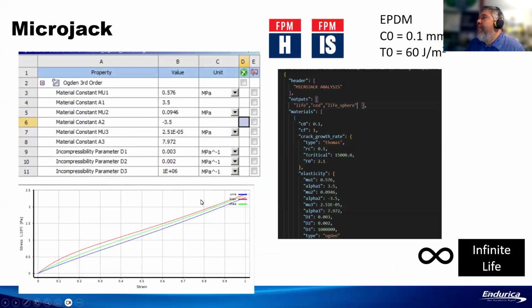So here's an example of the materials characterization. This is just showing the input fields in ANSYS. So obviously we need to know the stress strain behavior, and this is an Ogden model that we've happened to fit for this example. We've also measured, this is for an EPDM compound, and we've measured the fatigue threshold at 60 joule per meter squared. We've measured the initial crack size at a tenth of a millimeter.